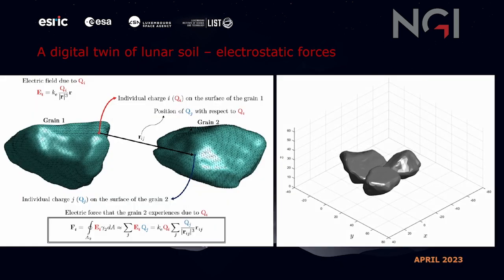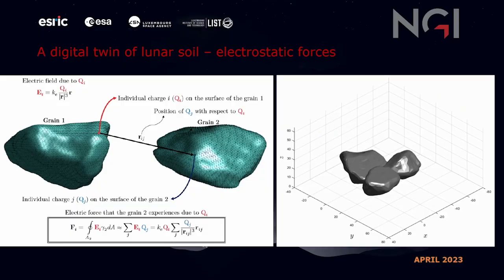We can also include something that has been found to be really important, especially on the moon surface, which is the electrostatic induced cohesion among the grains, which has been shown to affect equipment and the fabric from the astronauts' equipment and so on. So it is really important in this case. And we do that by including electrostatic effects or electromagnetic effects between and among the grains, adding surface charge densities with different signs and computing those electrostatic forces in the neighboring grains. So as we saw in the video on the left, with a toy sample, 3 real grains charged on the surface very differently, it works perfectly. Next.